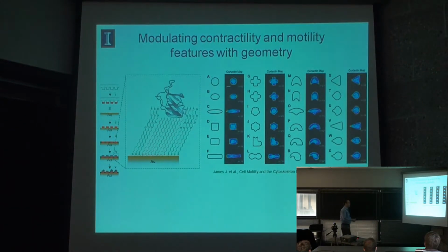And so the platform we use to do this is microcontact printing on thin layers of gold. We like gold because it's such a well-developed chemistry for self-assembled monolayers. And so in essence, we make a PDMS stamp, so just a regular silicone rubber stamp. We can ink that with a chemistry of choice. In this case, we use this octadecanethiol molecule, which can chemisorb to the gold surface and form a very stable gold-sulfur bond. And then by patterning that, we can then backfill the remaining regions outside with a non-adherent oligoethylene glycol moiety, which will prevent protein adsorption and cell adhesion.